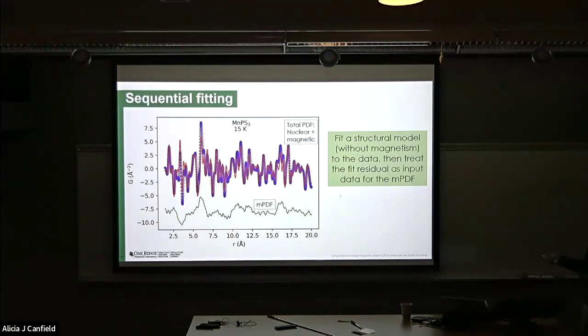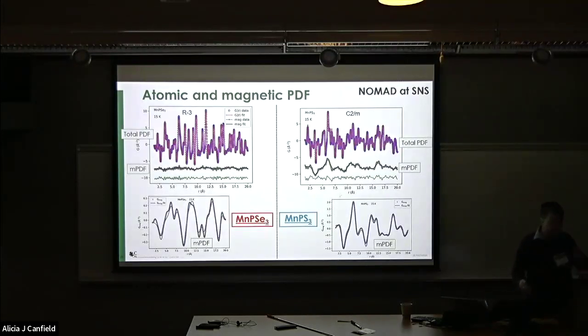So the way to do this is pretty simple, really. You just have your PDF pattern. This is the total PDF pattern from MnPS3, where your atomic, so your nuclear scattering, and your magnetic scattering is just mixed into this blue line. Then you just fit, the red is the fit to the nuclear scattering. And then what you assume is what is left over, the residual, is your magnetic part. So we say, okay, this is the MPDF part, and then we can fit this using the MPDF technique. This is what we did for this material, where we use the R-3 space group for MnPS3. We fit the nuclear part, the red, what's left over, the gray, we fit using the MPDF technique. And we're able to get a pretty nice fit, I would say, for the material. So we're able to use this technique to start to look at what's happening for the magnetic ordering.